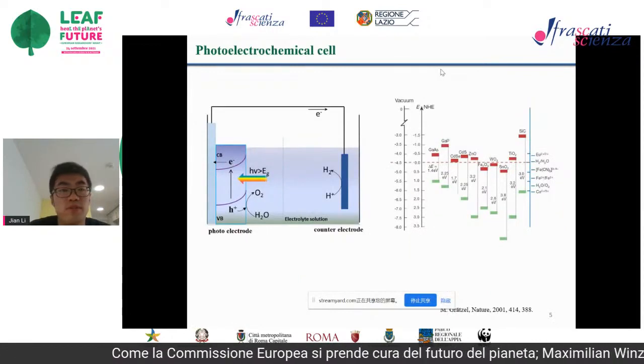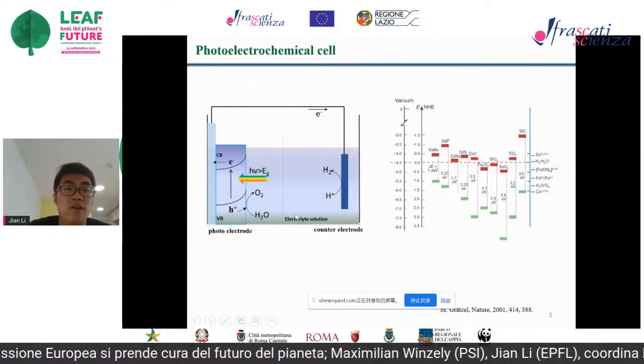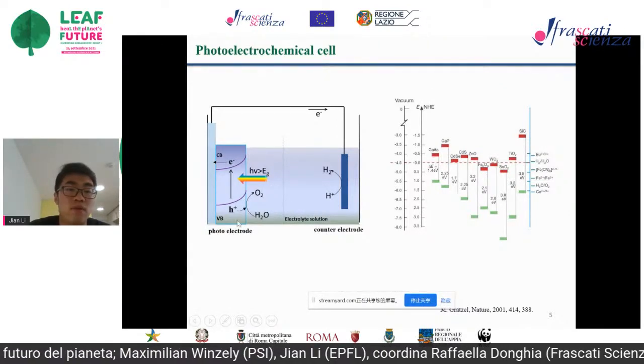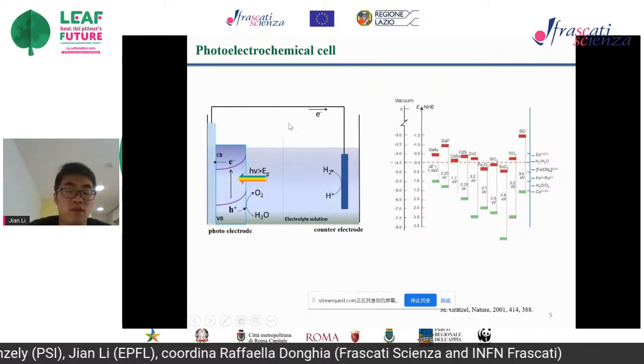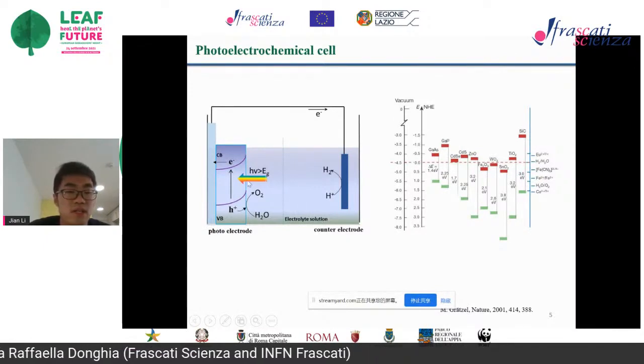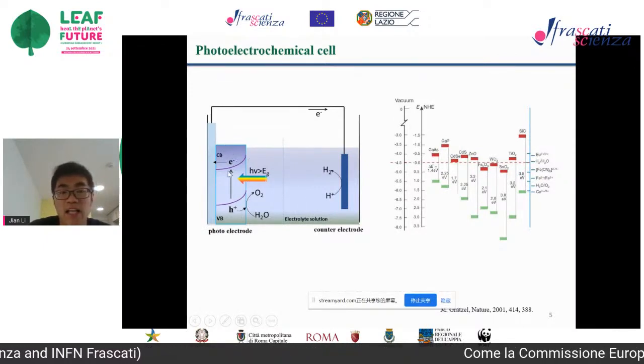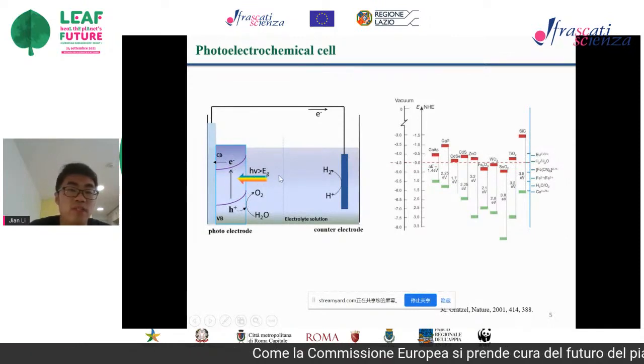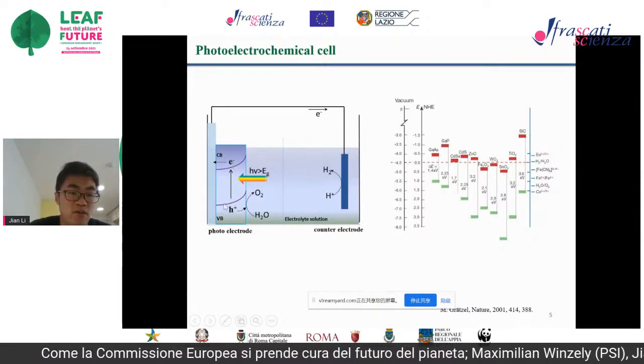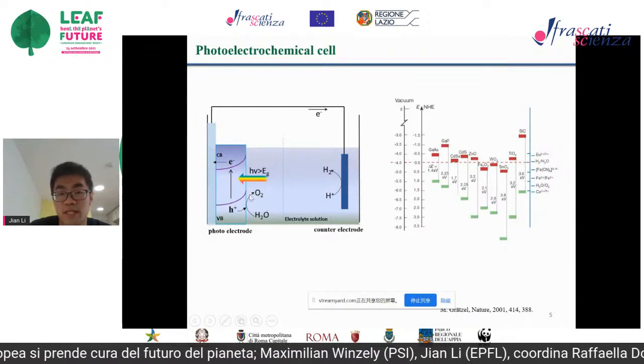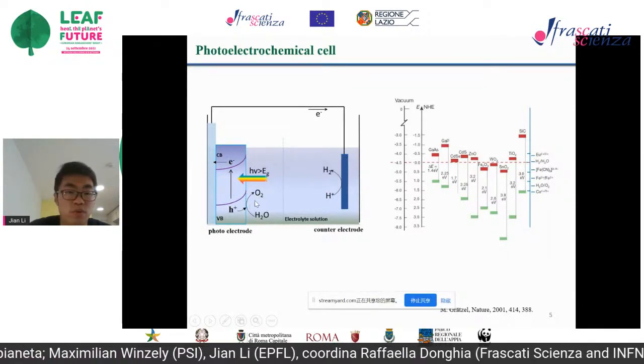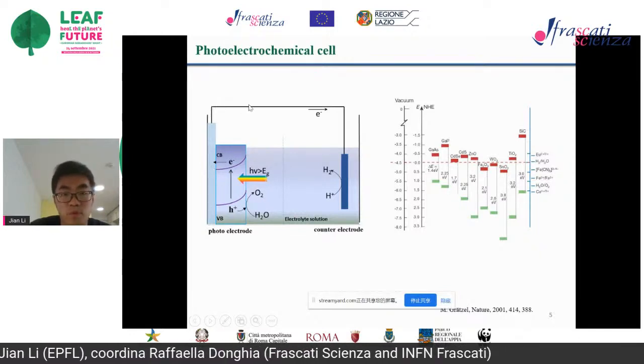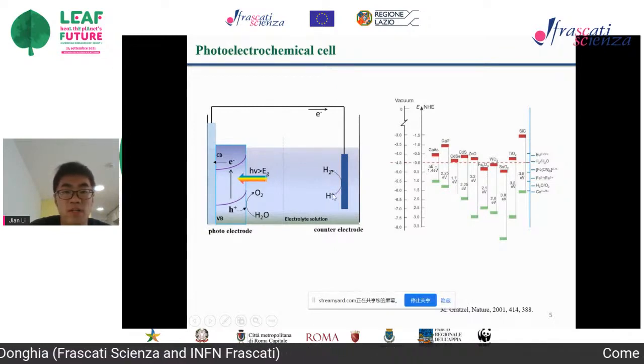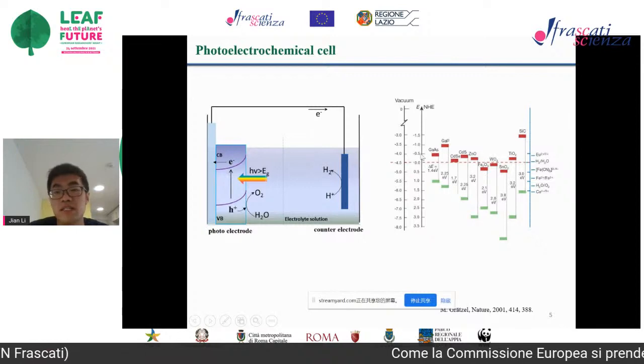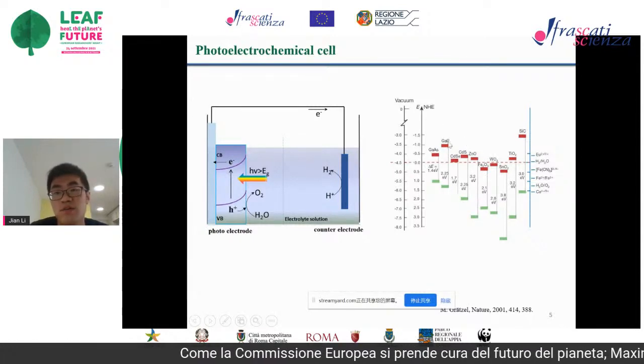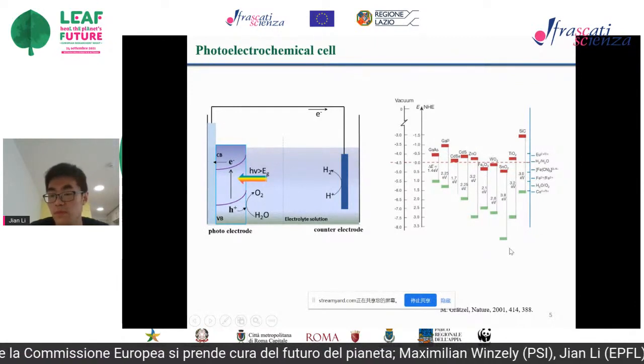In this part, I will introduce the PEC cell, that is photoelectrocatalysis. The PEC cell usually contains three electrodes: the working electrode, the counter electrode, and the reference electrode, which we don't show here. This is a photoanode, and it is also a semiconductor. When it absorbs light, it produces electrons and holes. The holes can migrate to the surface to participate in water oxidation to produce oxygen, and the electrons can transfer to the counter electrode to reduce water to produce hydrogen. This figure shows common semiconductors, their band gaps and energy levels.